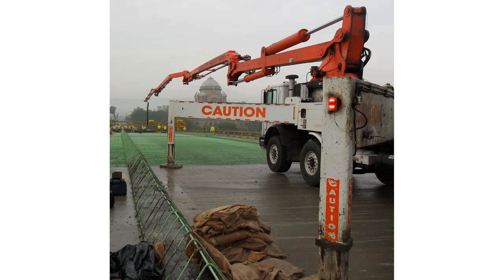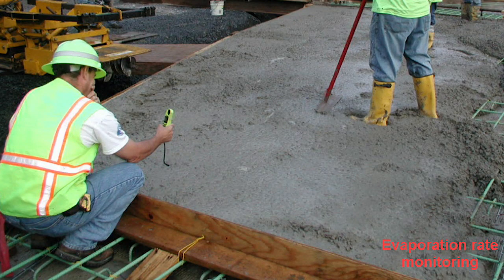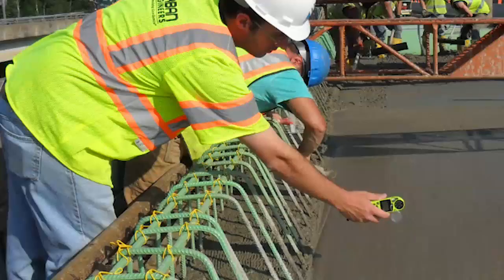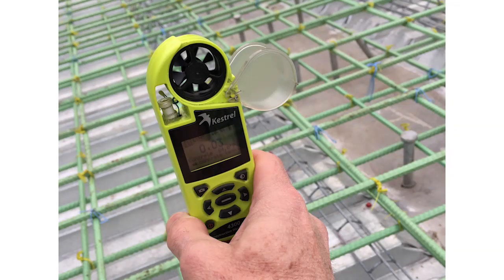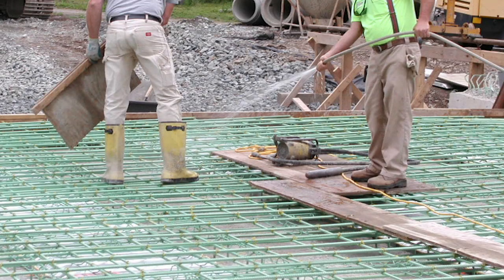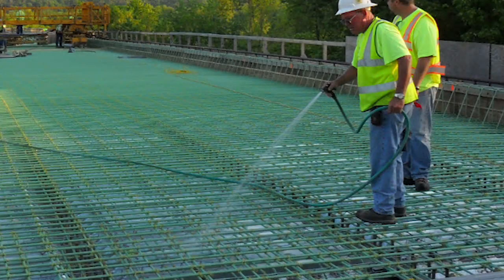deck. Determine the evaporation rate prior to placement, and then continue monitoring the evaporation rate every hour during the deck placement. Document the results. Do not exceed 0.06 pounds per square foot per hour. If required, pre-wet the bridge deck ahead of the placement.